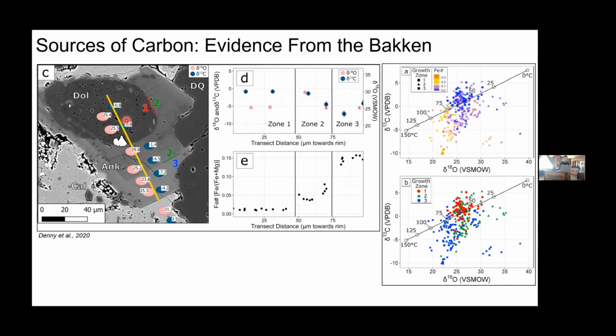And so what you're seeing along the length of this transect from the core out to the rims, looking particularly at this dark teal color in the rims, the carbon isotope, or the delta 13, is about 0, so something that is similar to seawater. And as you move further away from that core into the rims, you see a more depleted delta 13 of carbon, suggesting more organic influence.